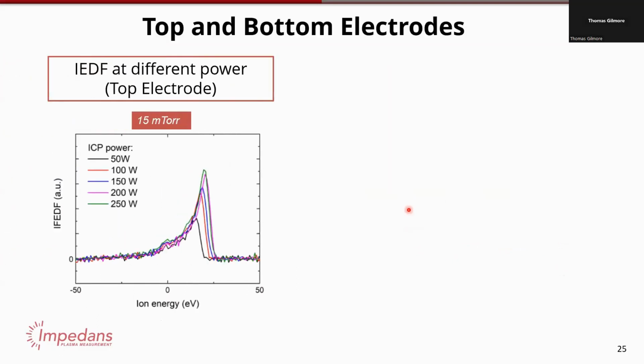So let me just show you some practical examples here. This is one where you have the IEDF, where you're changing the top electrode. In this case, it's an ICP, but you can see here, at 50 watts, you have this little thing. As you raise the power, you raise the ion flux. The area under this curve is the ion flux. As you increase the power, you can see the ion flux increases a lot, which is what you expect. The ion energy does not increase that much. I'll show a diagram in a minute to show how these vary versus power.